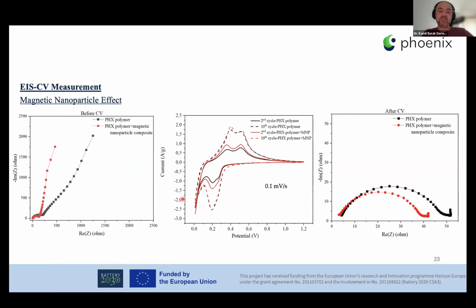And after that, we performed CV tests up to 10 cycles. The most important point in the CVs is that in the beginning of the cycle life, the cells with the magnetic nanoparticles are performing better than the others. But after 10 cycles, the results and the reactivity of the cells are more or less similar. So they are performing quite similarly.